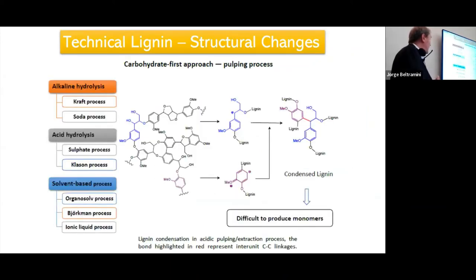The story is totally different if we have technical lignin, which comes mainly from industry. Alkaline hydrolysis, acid hydrolysis and solvent-based hydrolysis produce a variety of lignin. In this variety of lignin, the big problem is that we cannot produce the monomer, because the beta-O-4 bonding is already removed. So we don't have a good proportion of bonds to do the breaking, and here we have more polymeric lignin.